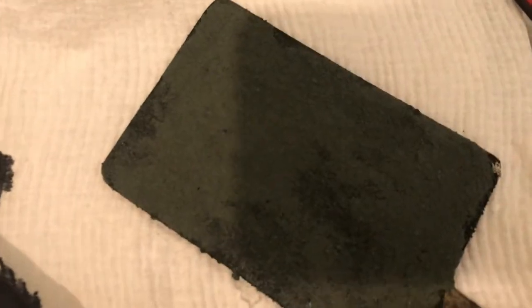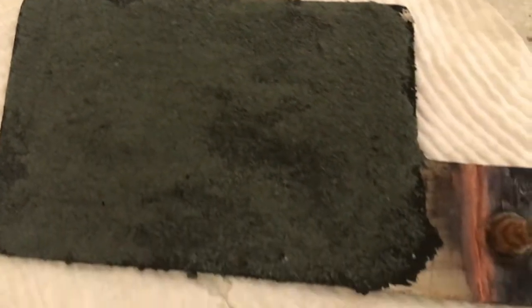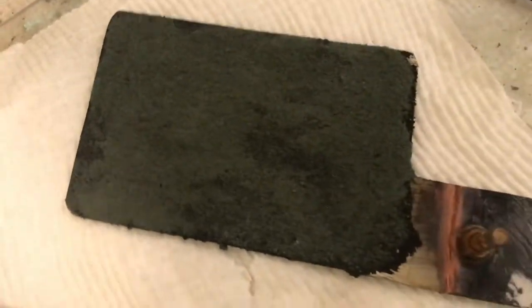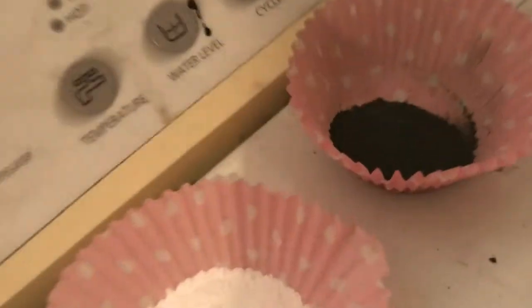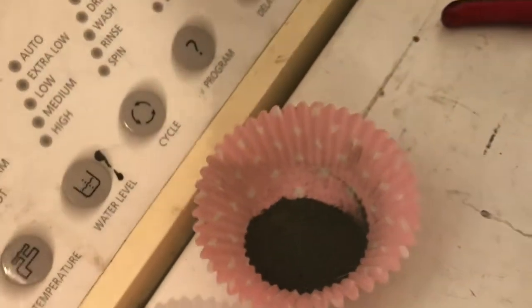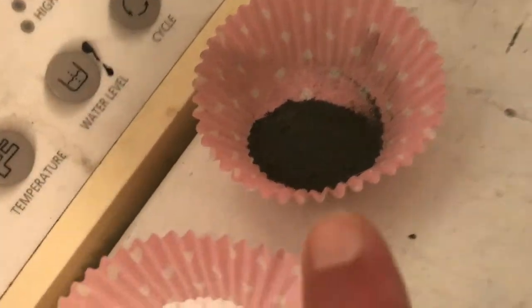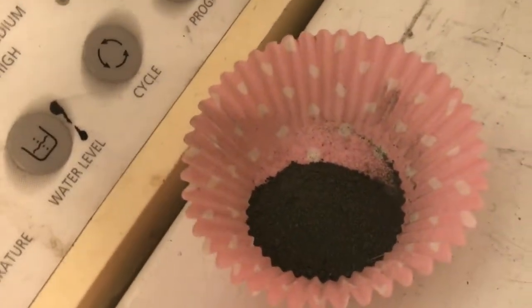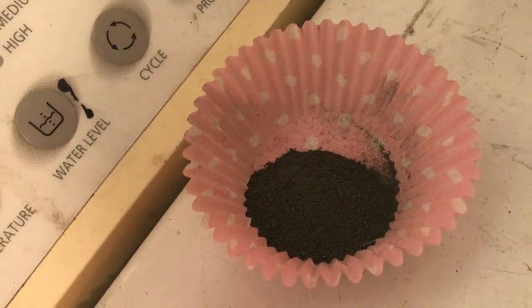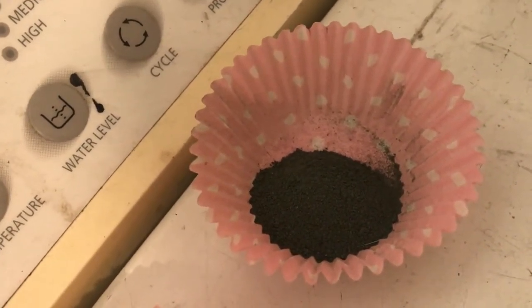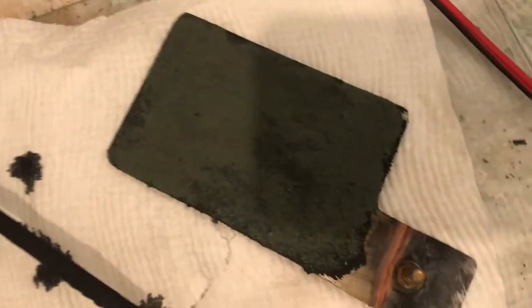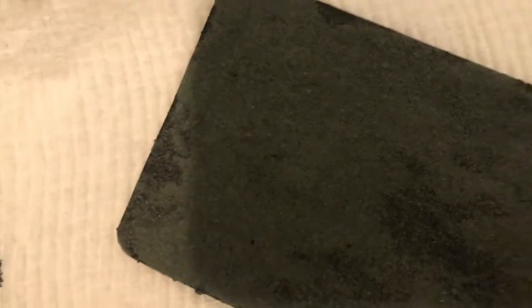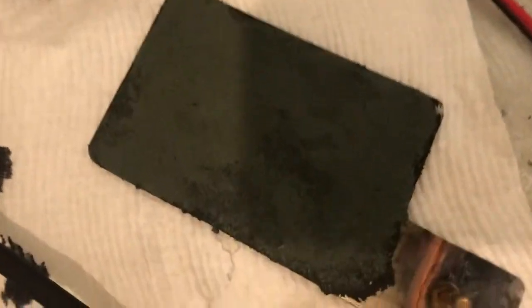Right, it's the next day. The ink's dried. There's 5 grams on both sides. The stuff I shook off, that's what came off. That's 7.61 grams of the nickel hydroxide and carbon mix. So there's around about 5 grams on both sides of that. I brushed it off with a brush. So that stuff stuck pretty well.